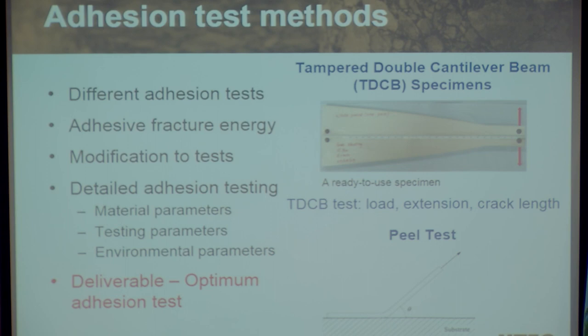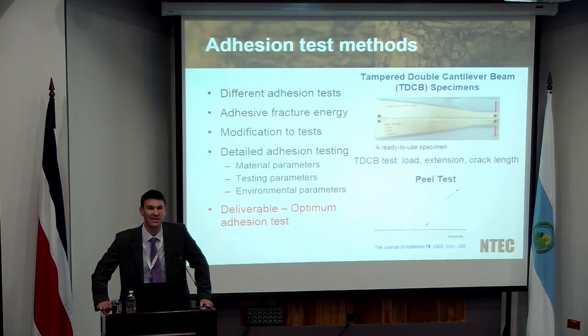So the study initially looked at a whole range of different approaches. It included the PATTI. So I'm not saying the PATTI is not a good test. The PATTI has some issues, because a pull-off test is always going to be very dependent on the accuracy of the geometry and making sure that your parallel plates in terms of your pull-off are kept parallel.